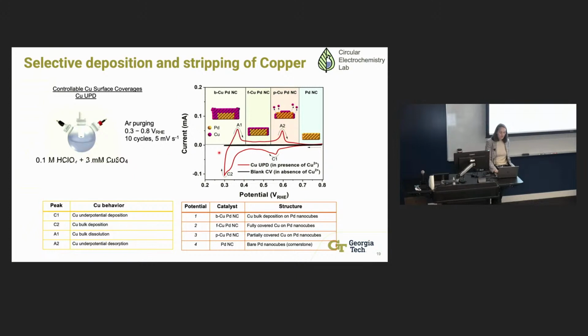And so this is an example of the manufacturing process in the lab that we use, where we can do various sweeps through oxidative and reductive potentials, and we can see really clearly both oxidative and reductive peaks, which says that current is being used to either deposit or strip metal from our surfaces. We can look at these various potentials. So C1 here is when copper is deposited, and that's right here. And C2 is the bulk deposition, and then bulk dissolution, and then the underpotential desorption.